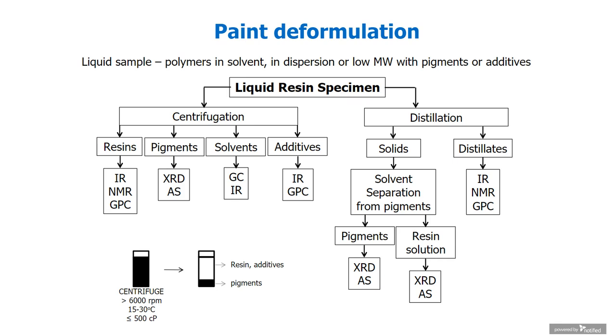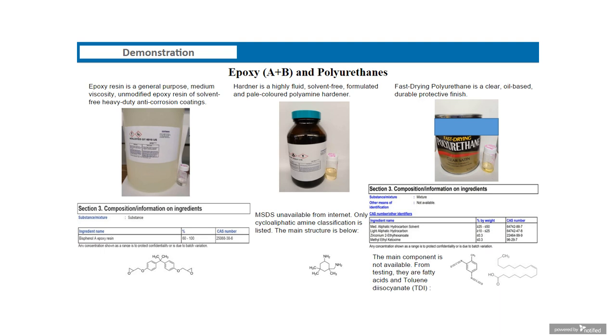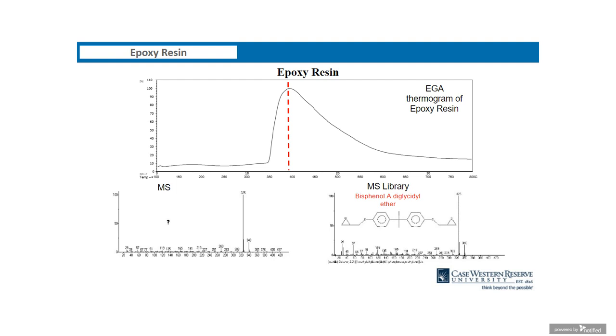Again, what this shows you is to do this job, you will do a lot of solvent extraction or sample preparation, and that can be discouraging. However, with GC mass spec pyrolysis, as I'll show you in some of these examples, this is done by simply scooping the sample from the source. And I tried to hide some of these product labels as best as I could, and I'll show you some examples. So for example, with an epoxy part A and B, epoxy and hardener. These are commercial samples and a fast drying polyurethane.